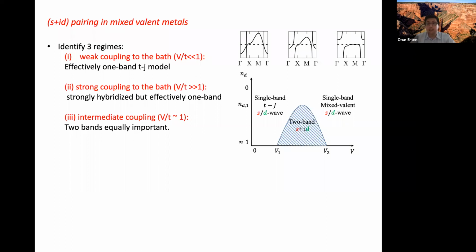And in this case, it becomes energetically favorable because one pocket shrinks near the gamma point, the other one goes to the M point. So wherever the nodes of the S wave are, there is no quasi-particle, so it becomes energetically comparable to D wave. I don't know if it helps, but we are not really doing BCS theory, but one can understand some limits of it from just doing fermiology, just looking at the Fermi surfaces.